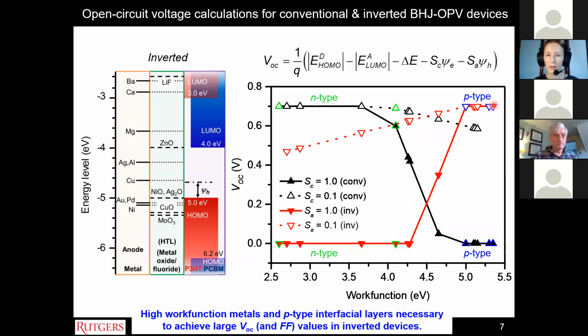For the inverted devices, the opposite case is true. You create a much higher open circuit voltage when you use a P-type interfacial layer between the polymer and the metal. The opposite side was a conventional zinc oxide used for the inverted device and MoO3 used for the conventional device. And we also factored in these potential interface dipoles, the case where we would have a very strong dependence on the work function and also a weaker dependence. You can see that even then the same trend holds, but it's a much weaker trend when you factor in the weaker interface dipoles.